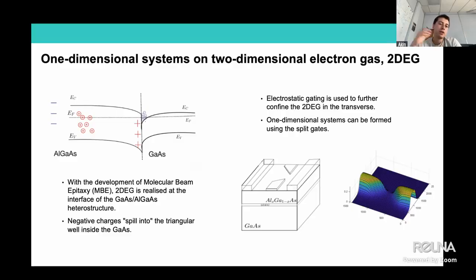And this two-dimensional electron gas can be created in a 3-5 heterostructure. The things I will be talking about today are on gallium arsenide and aluminum gallium arsenide. The aluminum gallium arsenide side of a heterostructure has a higher band gap than the gallium arsenide, so you will have the conduction band bending below the Fermi level. And it's grown by molecular beam epitaxy, which is the reason for such high quality of these materials as well. And there will be some dopant layer. There will be modulation doping, so silicon atoms will then donate those electrons into that well. So then we will have this well of electrons.